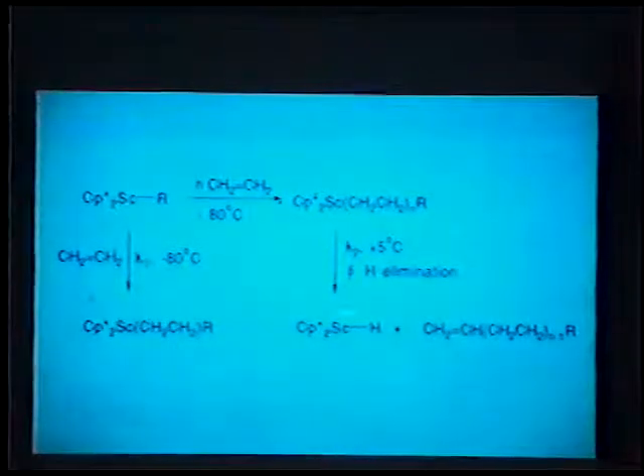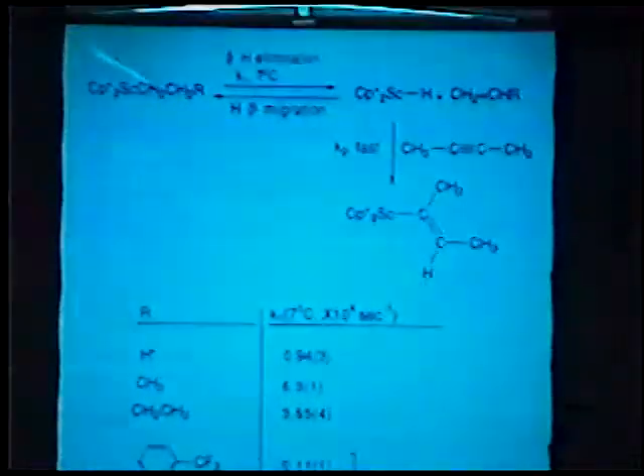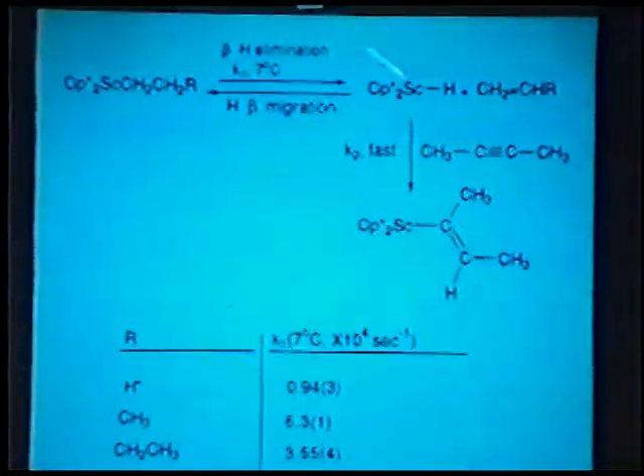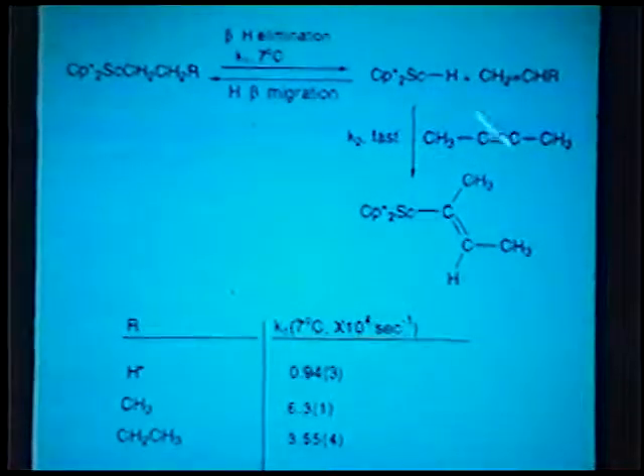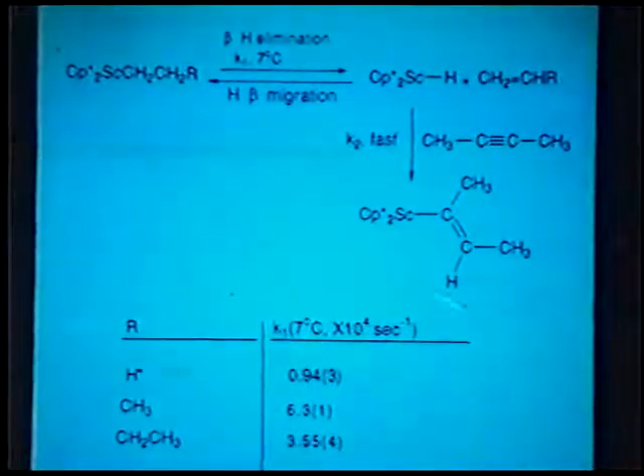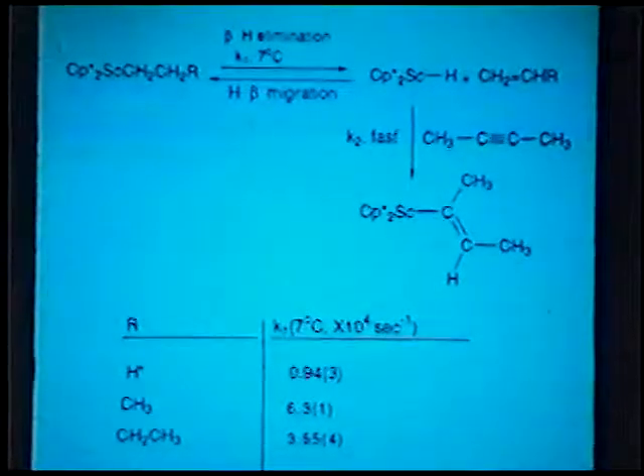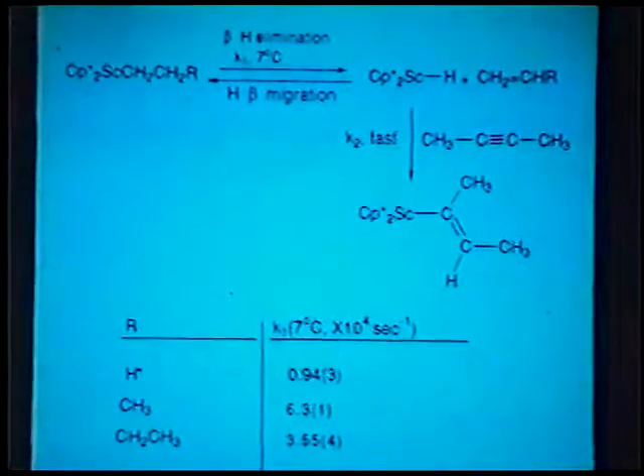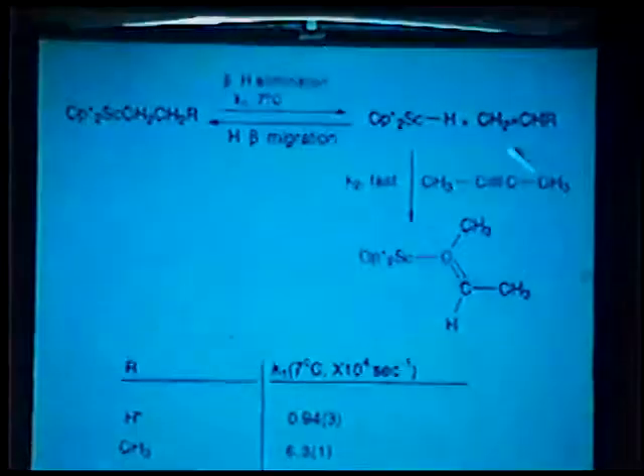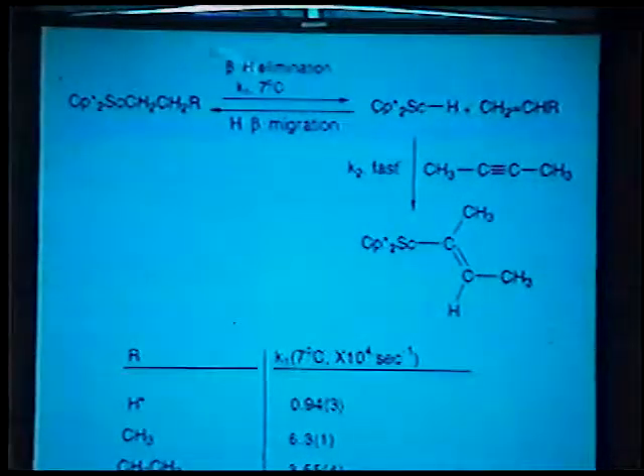We've also found at higher temperatures chain transfer by beta hydrogen elimination to release the alpha olefin, which competes. We've examined some of the features of this beta hydrogen elimination process by rapidly trapping the hydride as it's formed with a more reactive substrate, 2-butyne, to make this unreactive butene product. With just a few equivalents of 2-butyne, you find zero order in added butene, and that its k1 step is very limiting, conveniently enough.